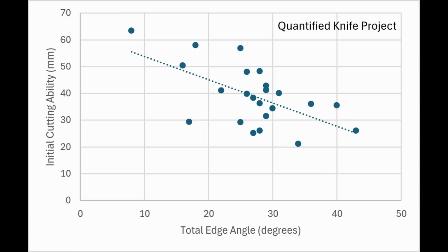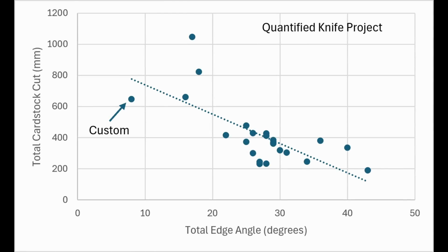So the more acute, the smaller the edge angle, the better the initial cutting was, which is what we would expect. However, when we plot edge angle versus Catra edge retention, the overall trend with edge angle is still very strong. We only have a couple of outliers. Both of those outliers, the one over 800 and the one over 1,000, are with a steel advertised as FC61, which is a proprietary name. I have seen speculation that that steel is similar to AEBL or 13C26, which would be surprising because those are relatively low wear-resistant steels, but we had outperformance relative to the total edge angle in these tests.